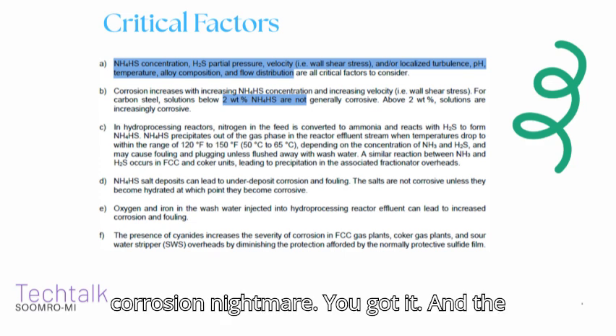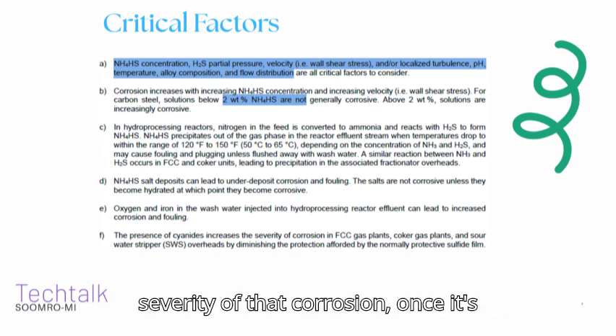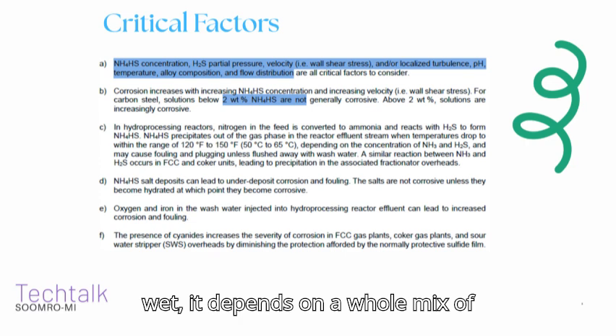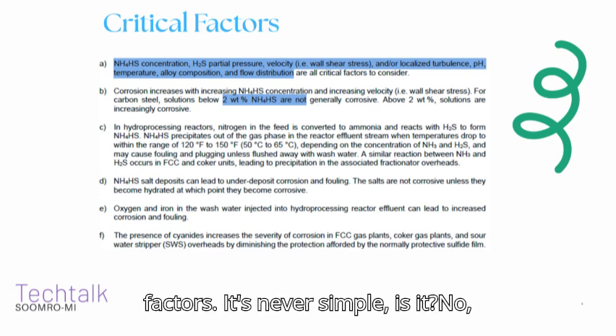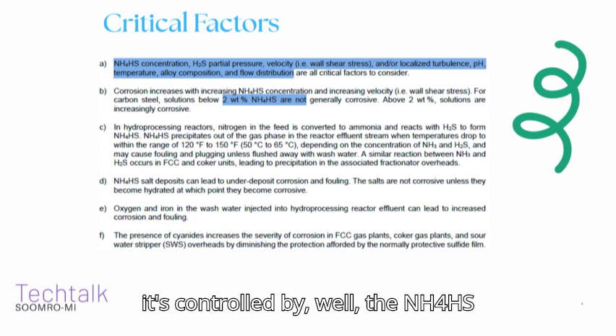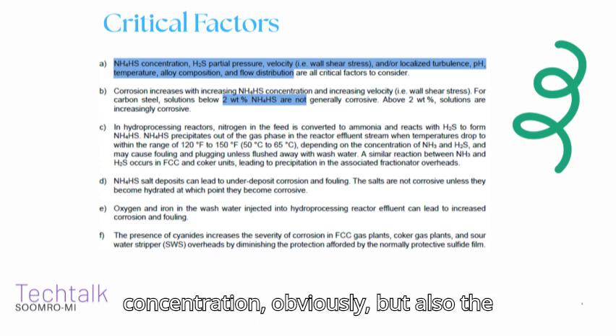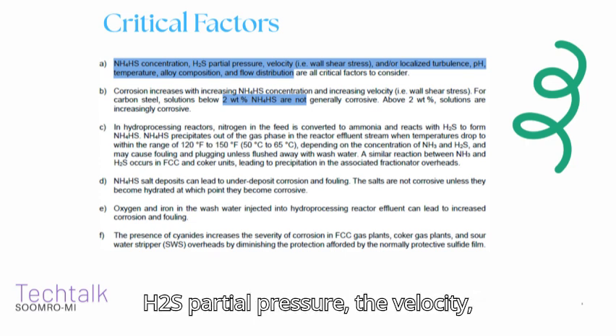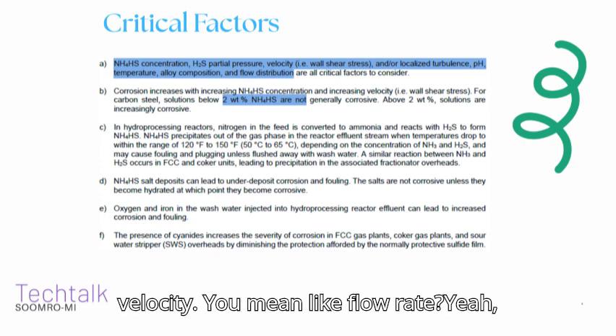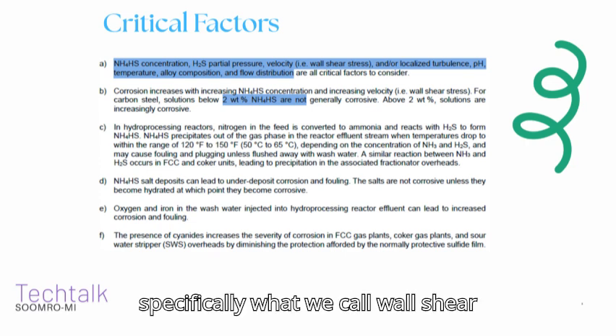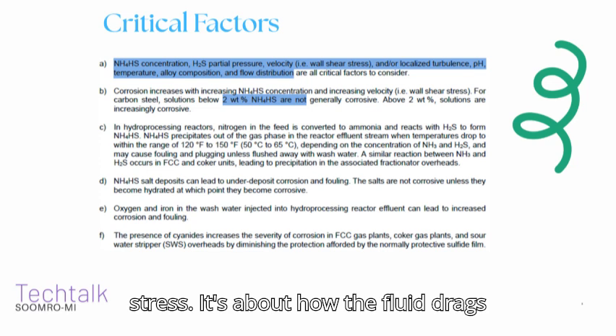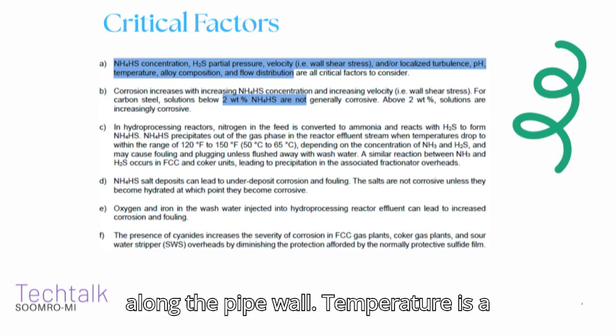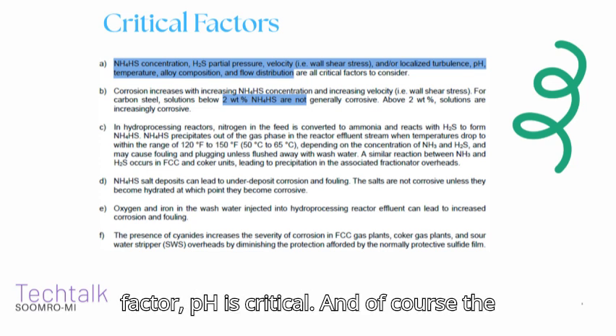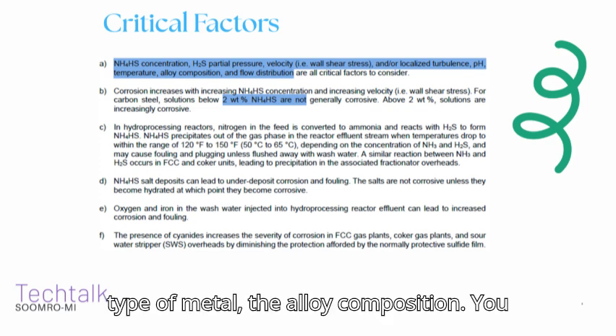You got it. And the severity of that corrosion, once it's wet, depends on a whole mix of factors. It's never simple, is it? No. It's controlled by the NH4HS concentration, obviously, but also the H2S partial pressure, the velocity. Velocity? You mean like flow rate? Yeah, specifically what we call wall shear stress. It's about how the fluid drags along the pipe wall. Temperature is a factor, pH is critical, and of course the type of metal, the alloy composition.